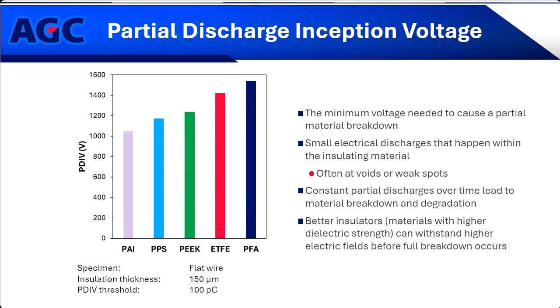However, continuous partial discharges over time will start to lead to material breakdown and degradation. So one thing I should note is, yes, partial discharges are more common at voids or weak spots, but they will always start to happen in any material, no matter the coating. So even if you have the most pristine, best coated material ever to exist, you will still get to a certain voltage where partial discharge will start to happen.